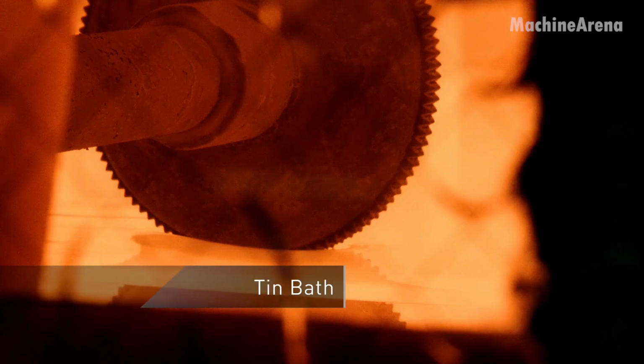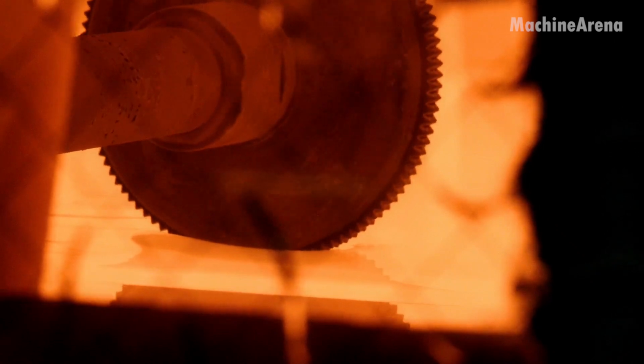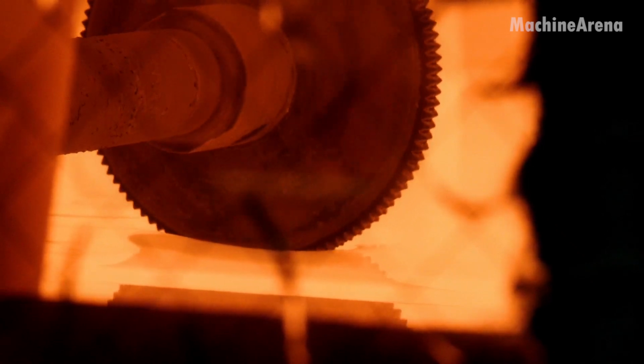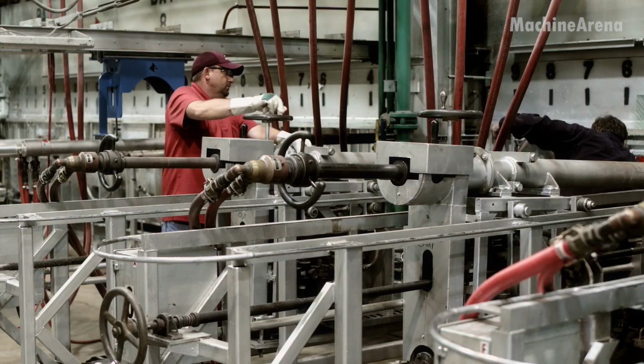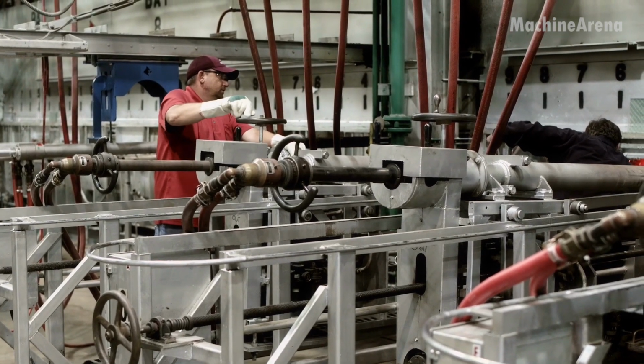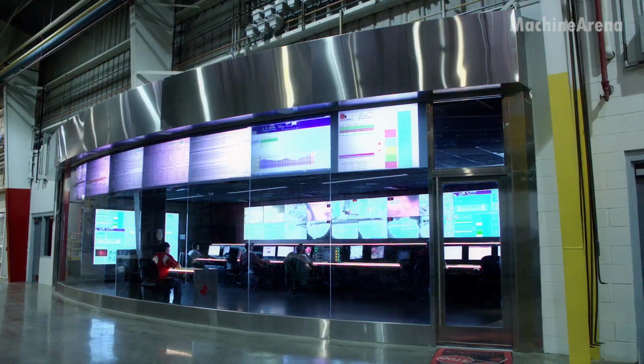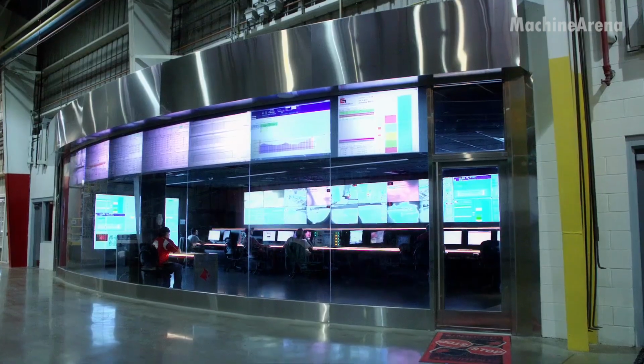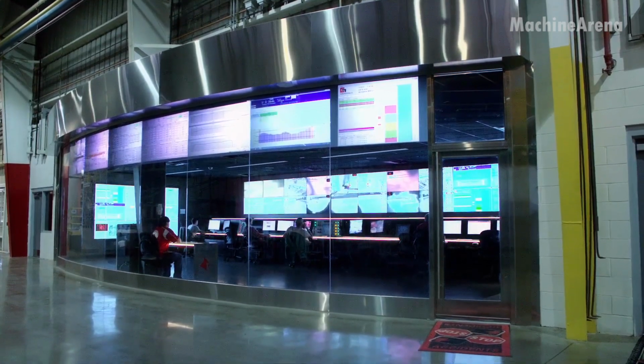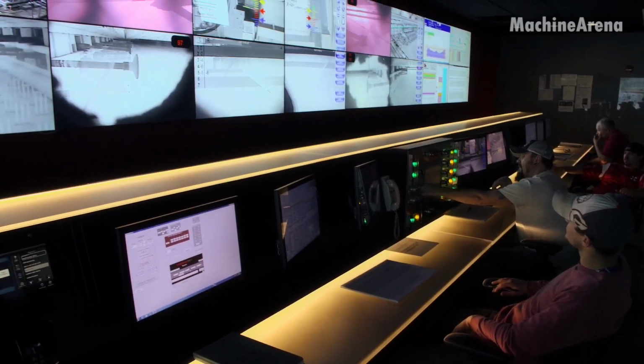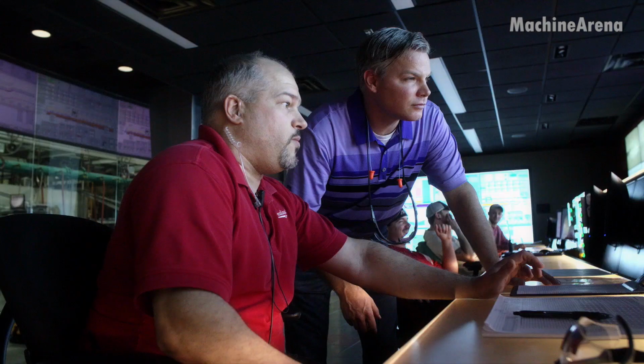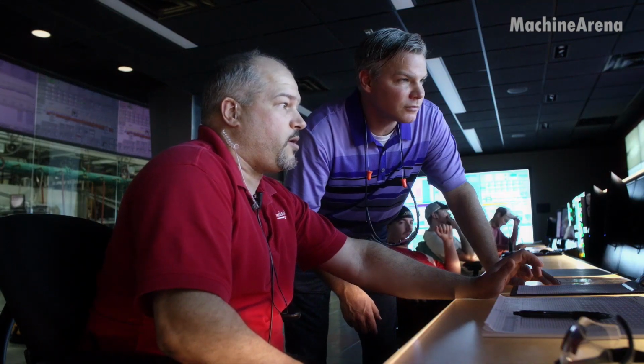But unlike glass blowing or mold casting, float glass is formed in a completely different way. The molten glass exits the furnace and flows onto a wide, flat bath of molten tin. Since glass is lighter than tin and doesn't mix with it, it floats perfectly on top. Gravity and surface tension naturally spread the molten glass across the tin, creating a sheet that is both uniform in thickness and smooth on both sides.